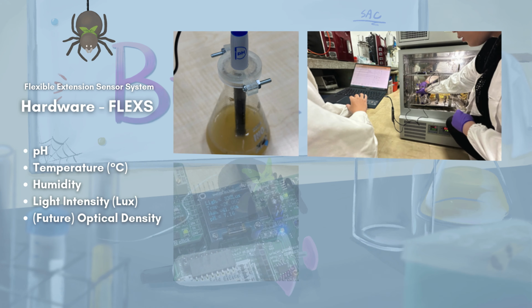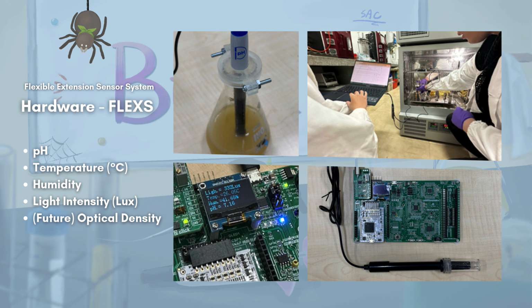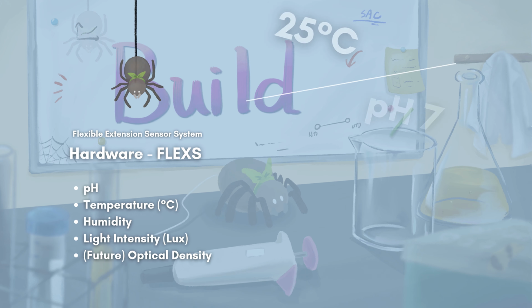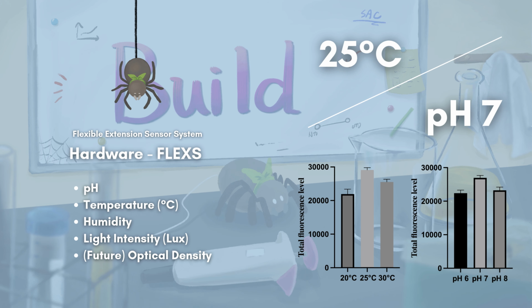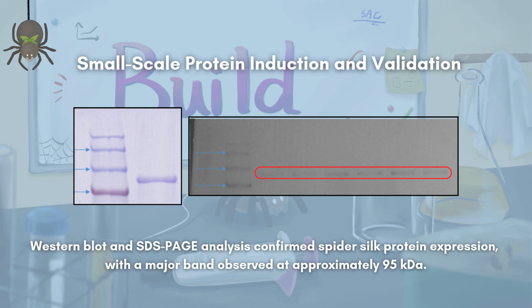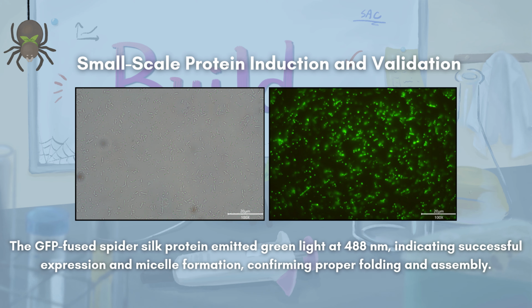We set up LB medium flasks with FLEXS, our real-time data collection hardware device, to monitor key parameters such as pH, temperature, and optical density OD. Using the GFP fluorescence intensity for quantification, we found that at 25 degrees C and pH 7, the protein yield was highest. Protein production was further evaluated using SDS-PAGE to assess expression levels, and Western blotting with GFP antibodies confirmed the presence of the spider silk proteins.